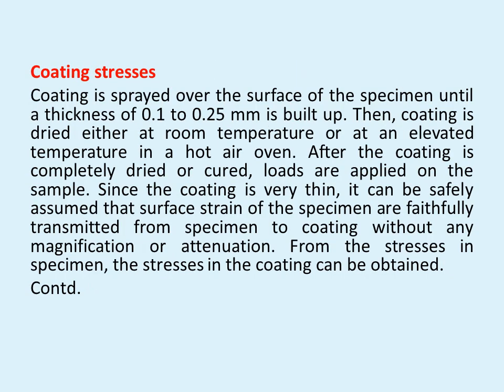We are going to apply the coating on the specimen of a thickness of around 0.1 to 0.25 mm and the coating is dried at room temperature or elevated temperature. After the coating is dried the loads are applied onto the specimen which is coated with the brittle. When the load is transferred from the specimen to the coating,